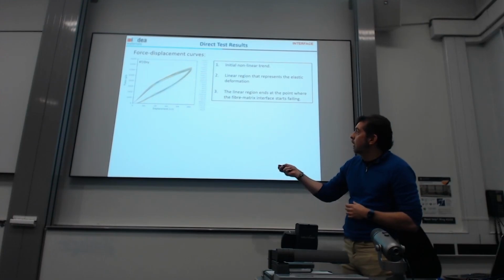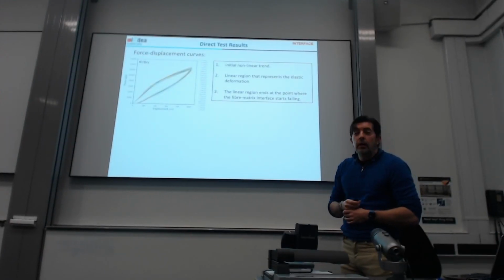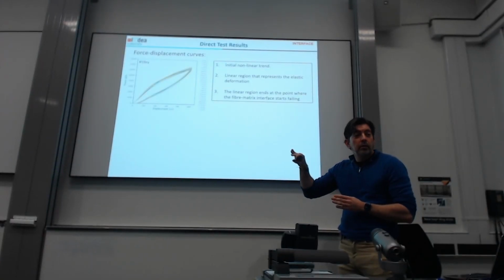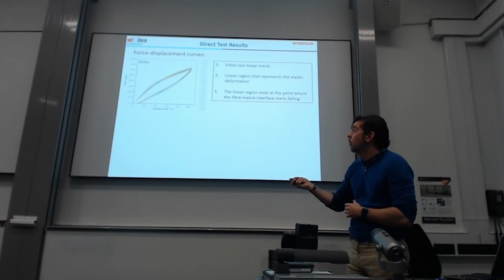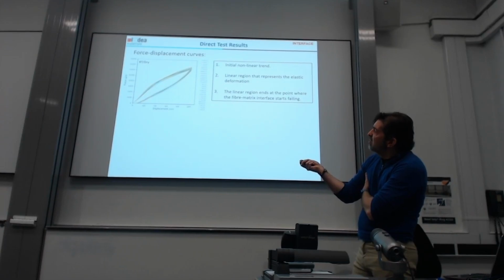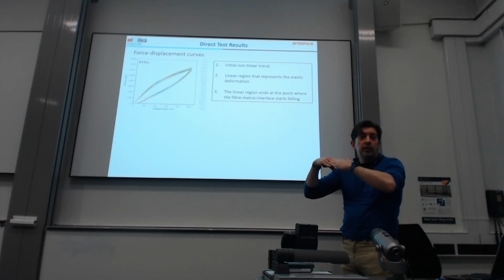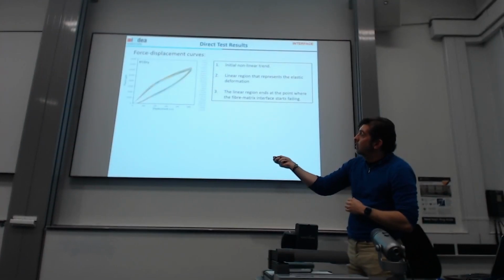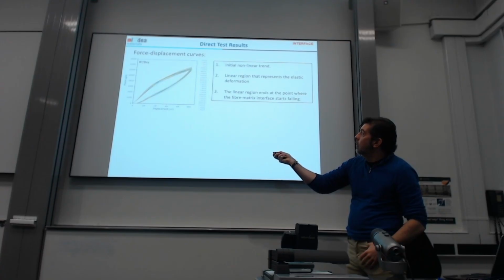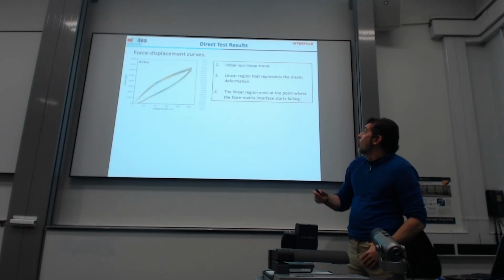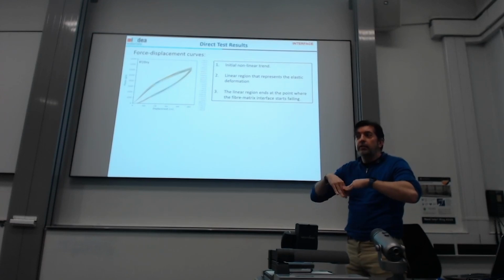What you get is obviously the load displacement. This is about 21 indentations. Very good reproducibility. So you have the initial non-linear region here because of the accommodation of the contact between the indenter and the fiber. Then you have the linear region, which is the elastic deformation, and then you have the start of the non-linearity where the fiber-matrix interface starts failing.